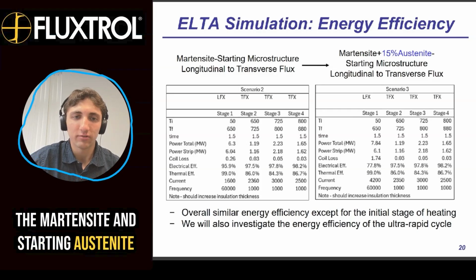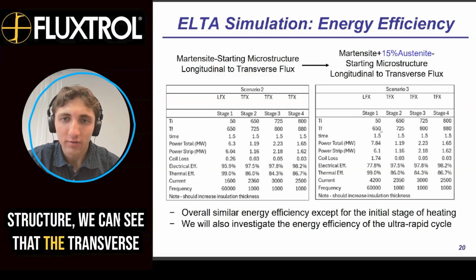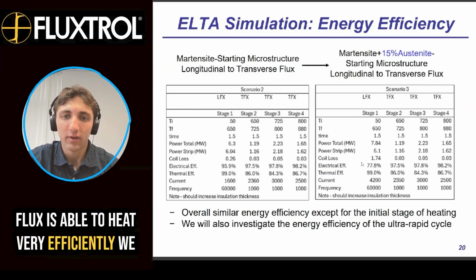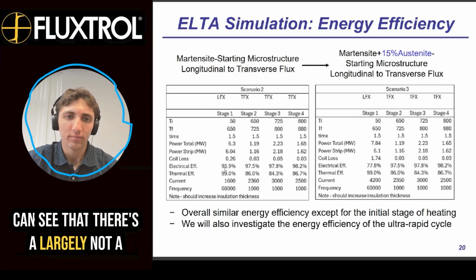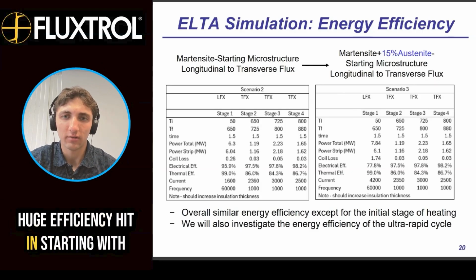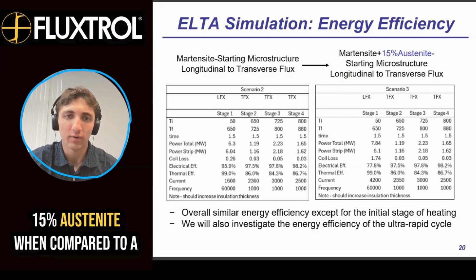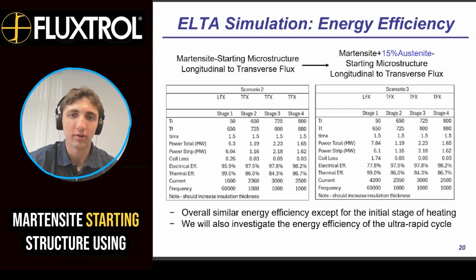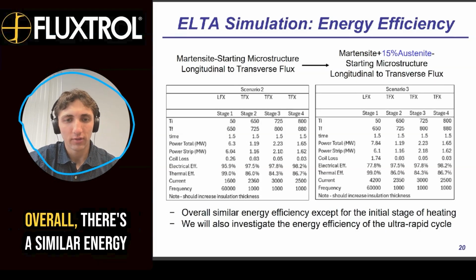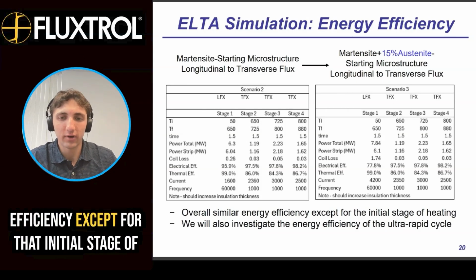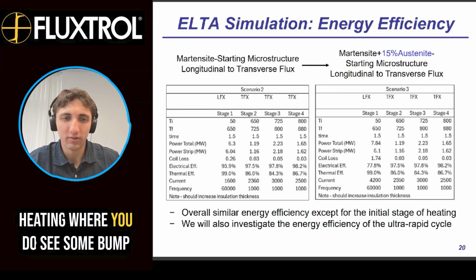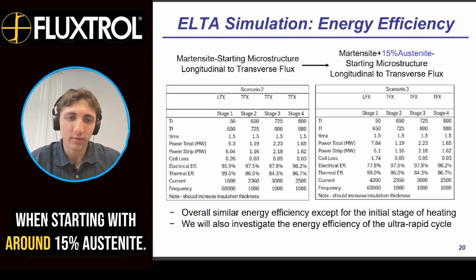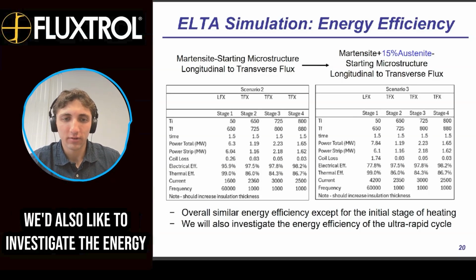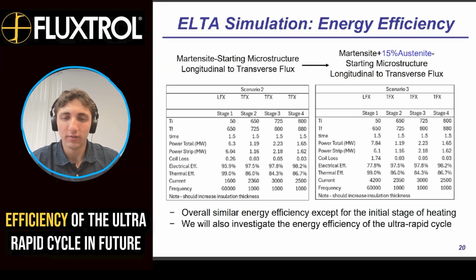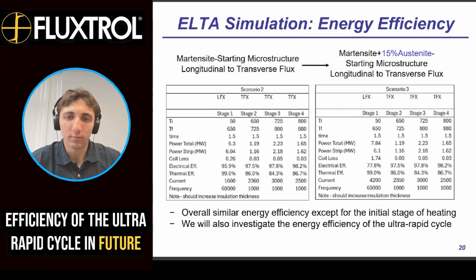And by comparison, when we look at the transition from longitudinal to transverse for martensite starting versus starting austenite structure, we can see that the transverse flux is able to heat very efficiently. We can see that there's largely not a huge efficiency hit in starting with 15% austenite when compared to a martensite starting structure using transverse flux. Overall, there's a similar energy efficiency, except for that initial stage of heating where you do see some bump when starting with around 15% austenite. And we'd also like to investigate the energy efficiency of the ultra-rapid cycle in future reporting periods.